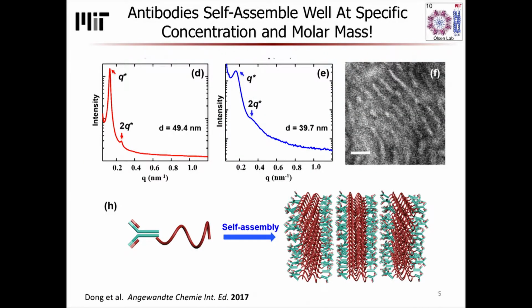We characterize these with small-angle X-ray scattering and transmission electron microscopy when they're self-assembled into solid-state thin films. So we take these molecules and we make them into basically block copolymer plastics that look and feel kind of like SEBS plastics, but are made of about half protein by weight. And X-ray scattering patterns of materials both in solution and in the solid state, and TEMs showing lighter stripes amidst darker regions, where these darker regions are the protein, these lighter stripes are the polymer, suggest the ability to self-assemble into lamellar-type layers.